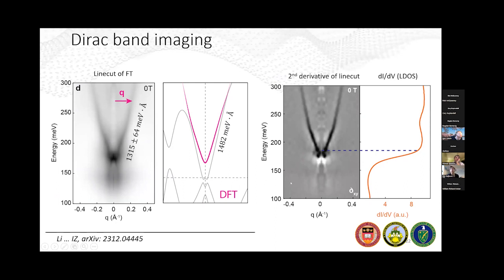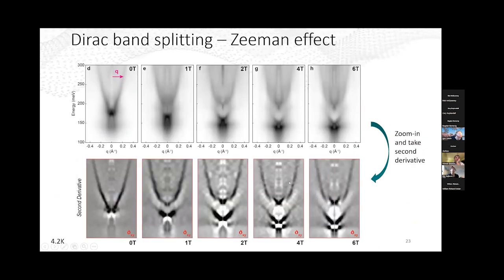As the last part of the experiment, we wanted to examine how this evolves as a function of magnetic field. And this is what I'm showing you next. So the top row are basically the same QPI measurements as a function of magnetic field, the same region of the sample, the same STM tip. On the bottom is this processing of the image above, which is something that ARPES measurements also often use.